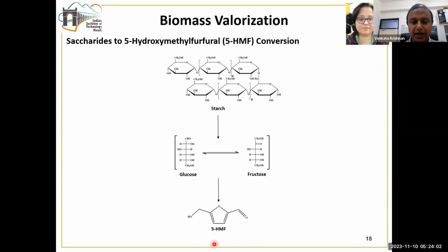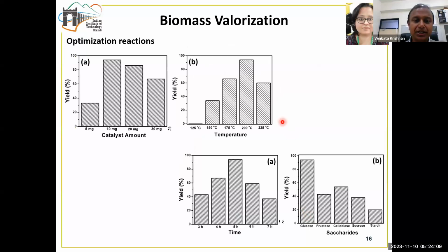Then we explored this reaction wherein the starch gets converted to glucose and fructose, which eventually get converted into the main product, 5-HMF, which is a selective product formed in the reaction. Then we did a detailed optimization of the different conditions. First, we optimized the catalyst amount and found 10 milligrams is the optimal catalyst amount. Then we optimized the temperature, wherein we found 200 degrees C is the optimal temperature for this reaction. We optimized the time and found 5 hours is the optimal time.